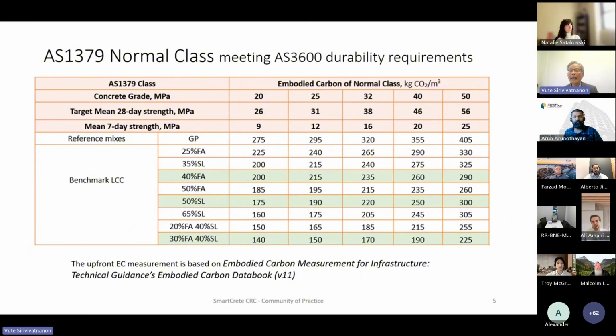Now, this is how we come up with our recommendation. We look at, in the case of normal class concrete, the different grade requirement, different target strength, 7-day strength requirement, and then look at a range of binder systems that we can use to produce the concrete to meet those requirements. In our calculation of the upfront embodied carbon, we have based the calculation on the technical guidance for the embodied carbon data book, which applies to work in New South Wales, as well as transport from New South Wales.